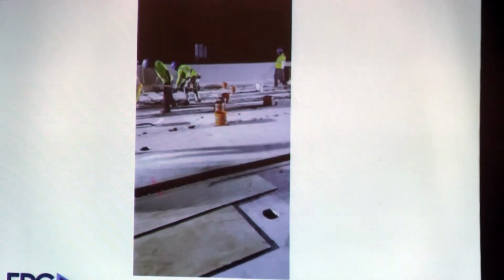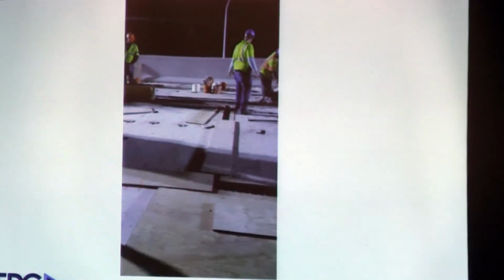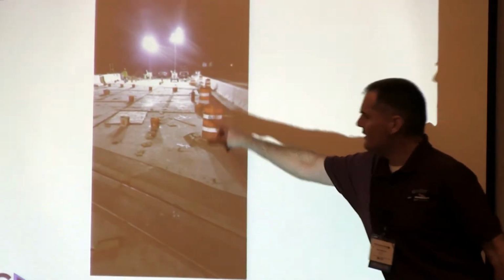But they were able to watch the UHPC flow through. We had guys underneath checking for leaks, but because it's water tested too, we didn't really have a big issue with that. And you'll see as we turn to the right, that right there is one of the intermediate beams.